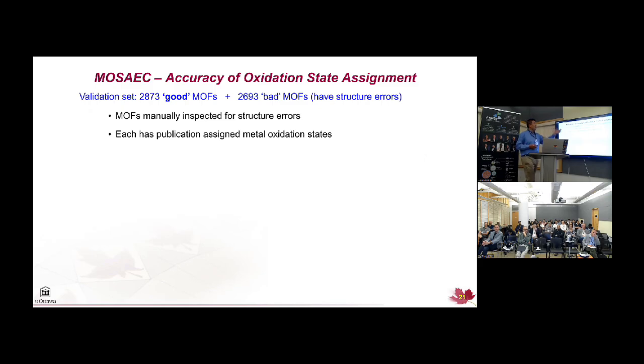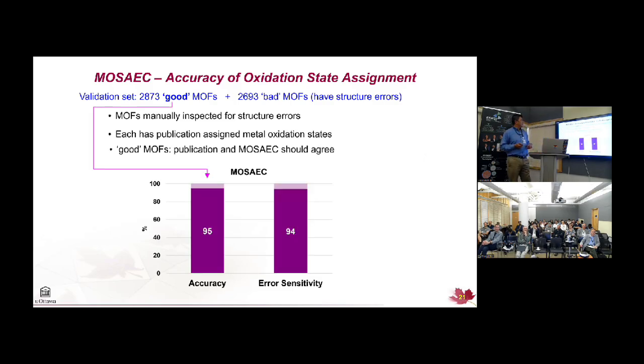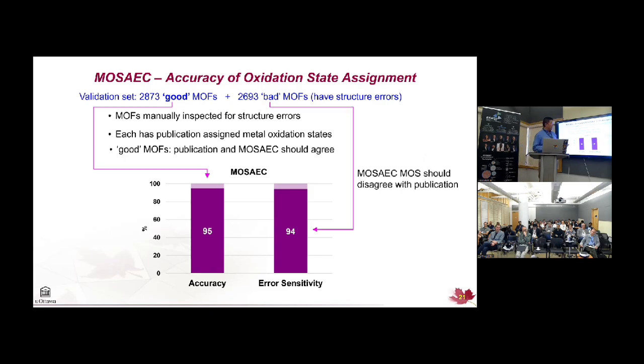Those original papers have, at least in the ones we picked, the oxidation state assigned. So we're taking that as the ground truth. And for the good MOFs, where we don't have a structural error, it's pretty accurate at assigning the right oxidation state. For the bad structures, that error should make the oxidation state we calculate wrong. And in fact, it's wrong 94% of the time. So that's exactly what we wanted, to be able to detect errors.